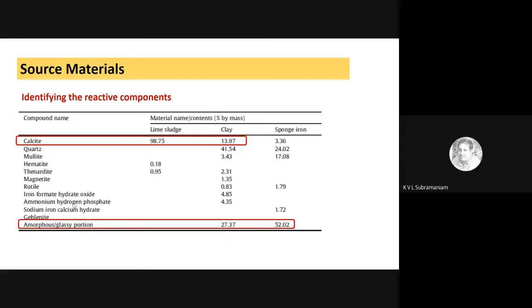Here are the actual useful materials that are coming from these raw materials that I used. Lime sludge contains 98.75% calcite, which is calcium carbonate, which I can use. Clay contains 13.97% calcite, which is useful. And the sponge iron contains a small quantity, which is 3.36% calcite. So basically, I'm getting my source of calcium from these. And if you look at the amorphous glassy portion, which I have highlighted below, which contains the reactive silica, clay contains about 27%, and sponge iron contains about 52% of this reactive silica. So I'm basically bringing in reactive calcium and reactive silica, which I need to produce my calcium silicates.